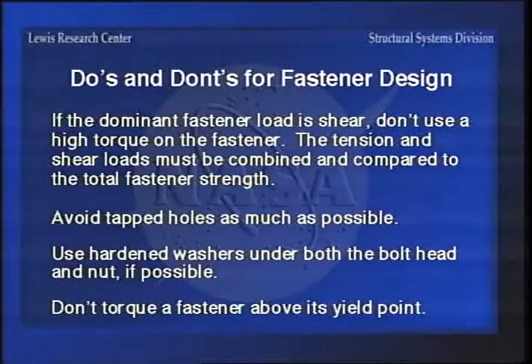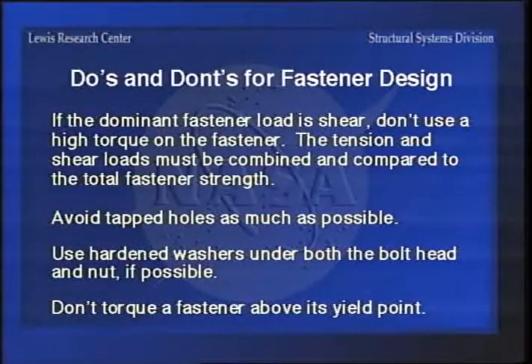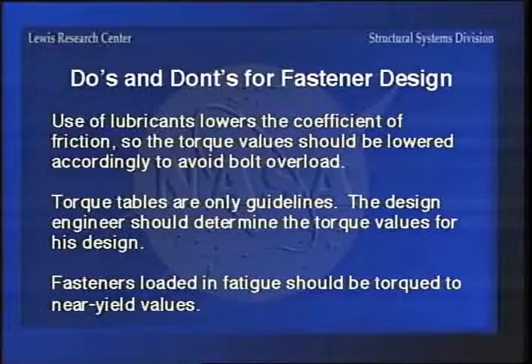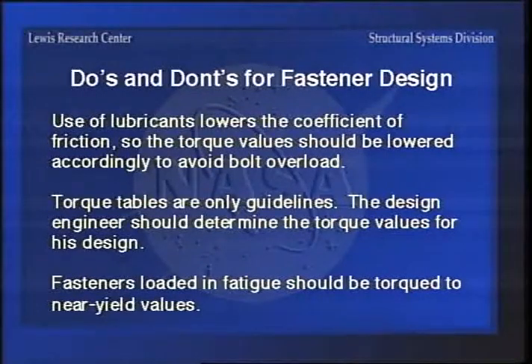Use hardened washers under both the head and the nut on a bolted installation if possible. Don't torque a fastener above its yield point - stay below the yield point and don't get close to it unless you run sufficient tests to determine pretty much where it is. Then in a fatigue joint, if you have to go up because of fatigue, you can go up to a near-yield torque. The use of lubricants lowers the coefficient of friction so the torque values have to be adjusted accordingly. We had a case at the Cape with silver-plated stainless steel nuts - a manufacturer coated these silver-plated nuts with wax to keep them from tarnishing, but nobody told the guy using the torque wrench, so they were yielding these things all over the place. The wax actually reduced the coefficient of friction to about half of what it would normally be.